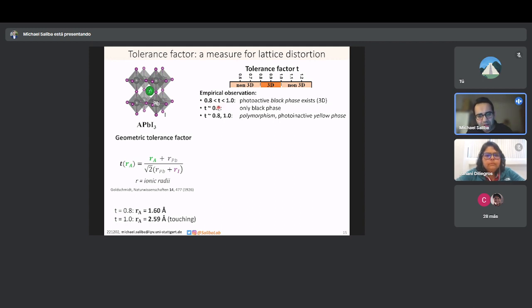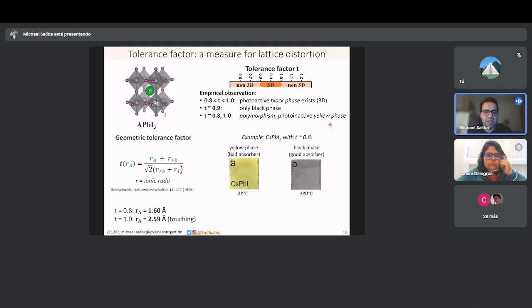A tolerance factor of 0.9 gives only a black phase. Unfortunately, at 0.8 and 1.0, there's polymorphism, the coexistence of multiple phases. In the case of perovskite, it's an alpha and a delta phase. The delta phase, because it looks yellow, is also called the yellow phase. And the alpha phase, you see that here, is the black phase.